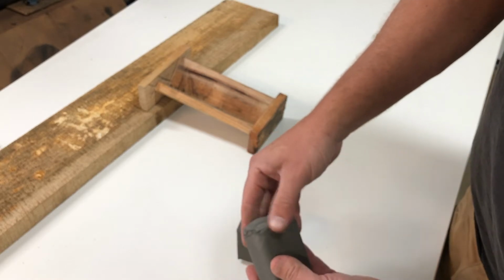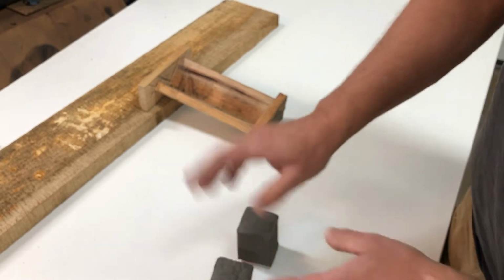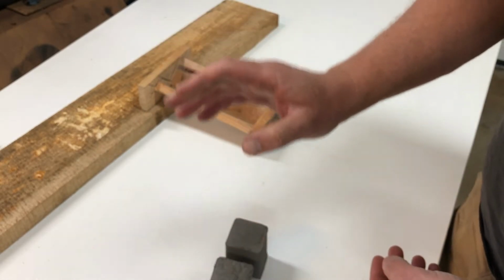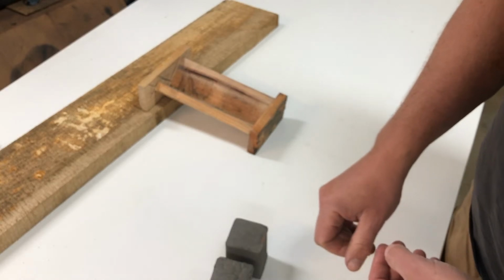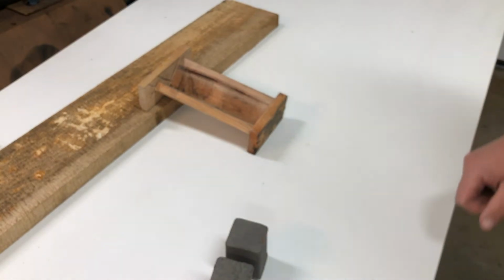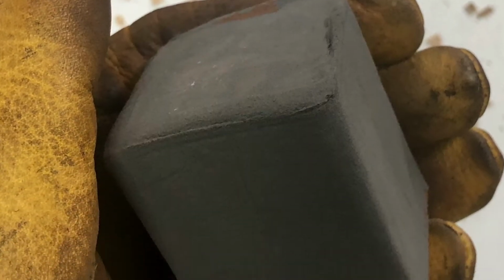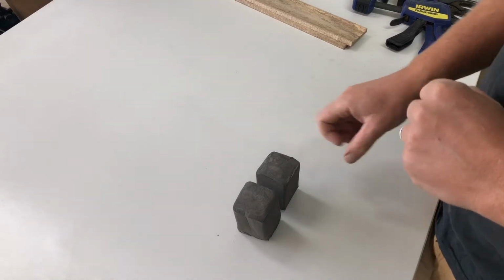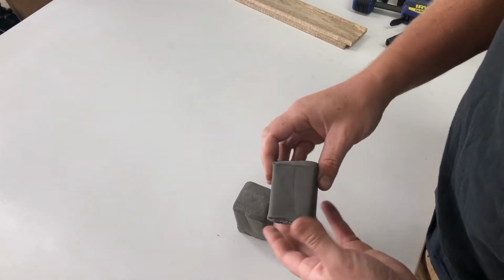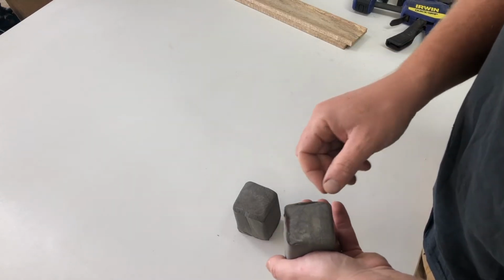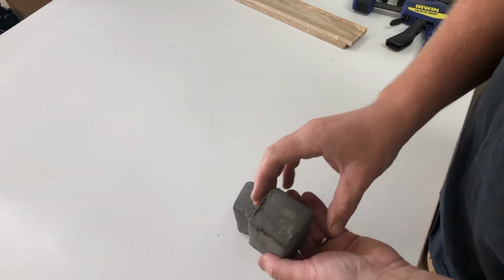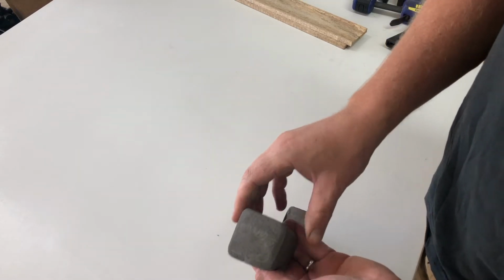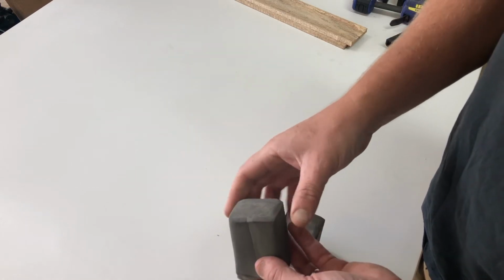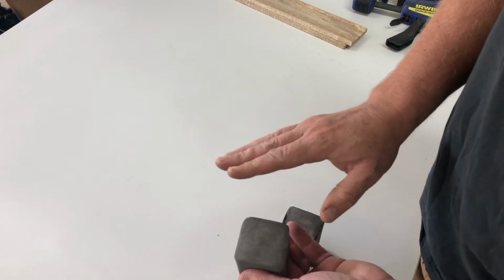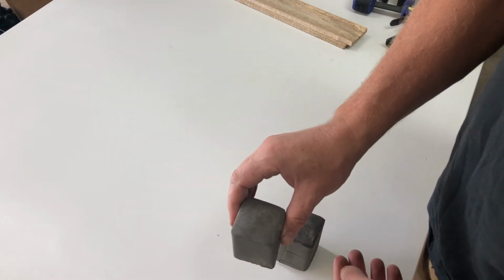You can see some of the little bits on the outside fall off, but at this stage and going forward, the blocks are actually pretty robust, so I don't need to be all that careful with them. So at this stage, I've finished the initial baking drying. These have been baked up to 250 degrees Fahrenheit, and that should have driven off all the water, all the moisture in there, but has not started to burn out the methyl cellulose.